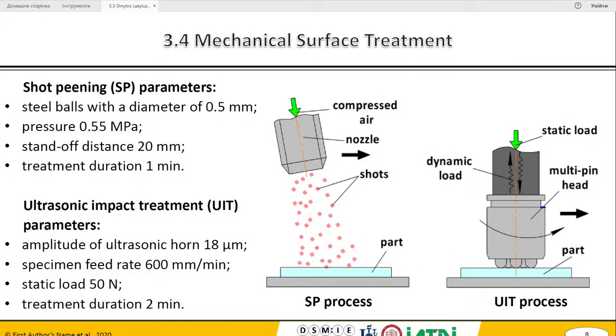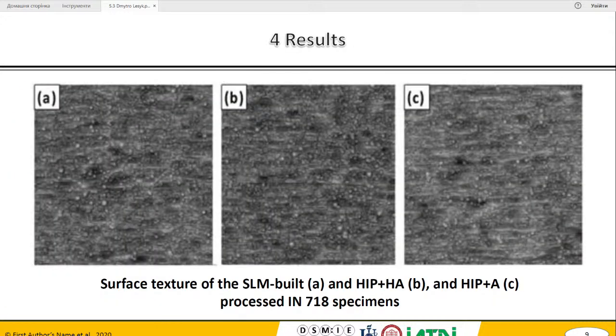So, two mechanical post-processing techniques such as conventional shot peening and ultrasonic impact treatment were applied in the optimized parameters for surface treatment of heat-treated specimens. The schemes of the shot peening and ultrasonic peening process are shown on the slide. Next, please. So, surface topography of the SLM built and heat-treated specimens is given on the slide. It can be seen that manufacturing surface defects such as ellipsoid or spherical balls, partially melted powder particles, open pores, as well as signs of laser tracks remain on the surface after post-heat treatments. Next slide, please.